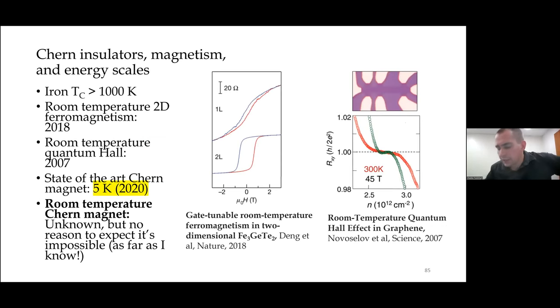Right. So a point that I think is worth making is that none of that, as far as I know, is intrinsic to the physics that I've been discussing. So magnetism itself is a very high energy phenomenon. There are all kinds of transition metal magnets that survive up above 1,000 Kelvin. And indeed, room temperature 2D ferromagnetism has already been observed in a couple of different systems now, but originally in this iron germanium telluride system, which is shown here.